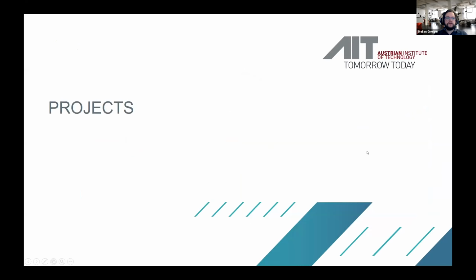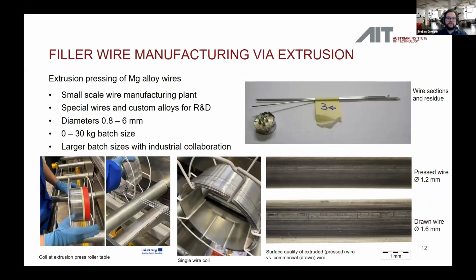So now I come to the projects we are working on currently. The first project is the wire manufacturing via extrusion pressing. For materials development, it is necessary to obtain small amounts of wires in a rather flexible way. Therefore, we have established a processing route for manufacturing welding or filler wires with extrusion pressing. The diameters we are capable of manufacturing range from 0.8 to 6 millimeters, and the batch size is from 0 to 30 kilograms, which is completely suitable for our needs for research and development, especially for welding and wire additive manufacturing.